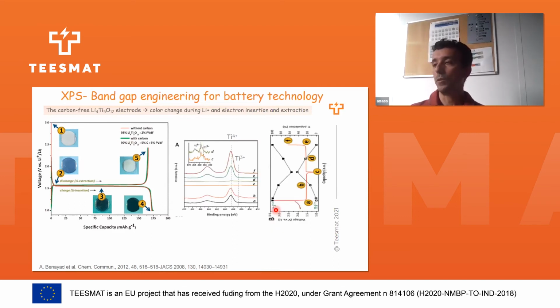In the XPS, we follow the redox process on titanium 4+ and 3+ during the first discharge and the charge. Here is the initial point of the titanium peak. We have mainly 4+. When we discharge, we have a reduction of the intensity of titanium, and suddenly at points D and C, in the middle of the galvanostatic discharge and at the end of discharge, the titanium is not observed anymore.